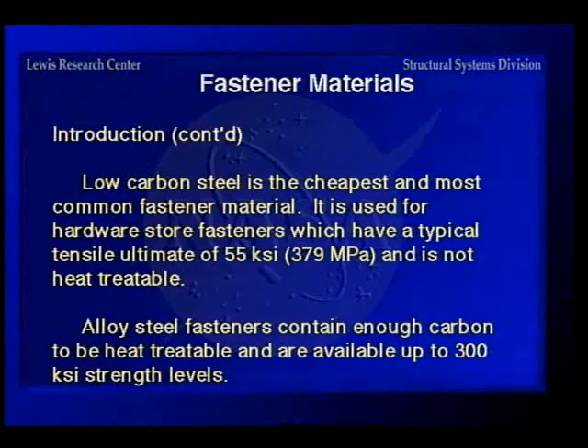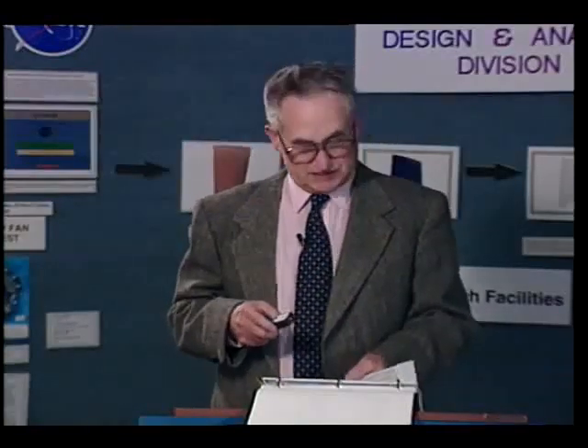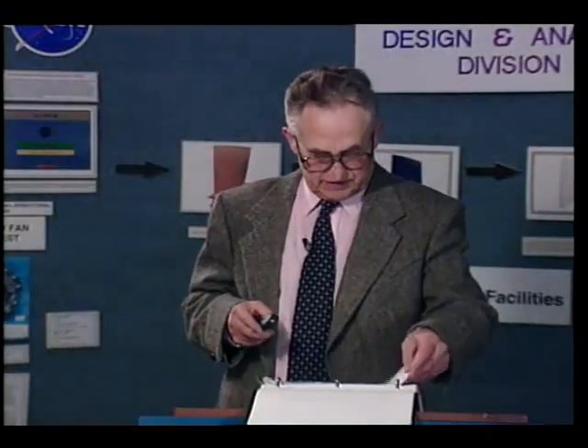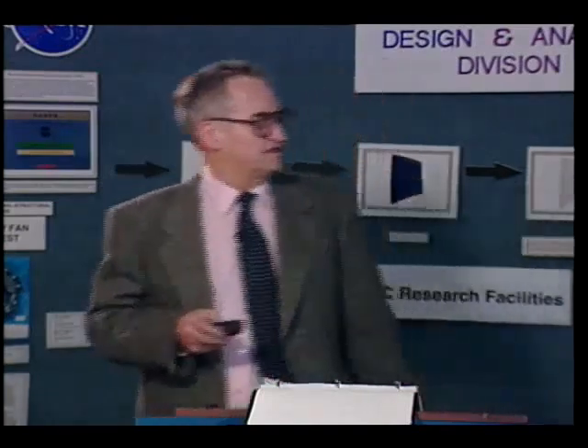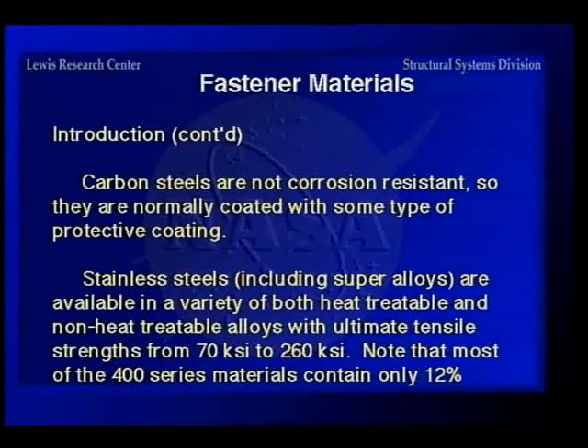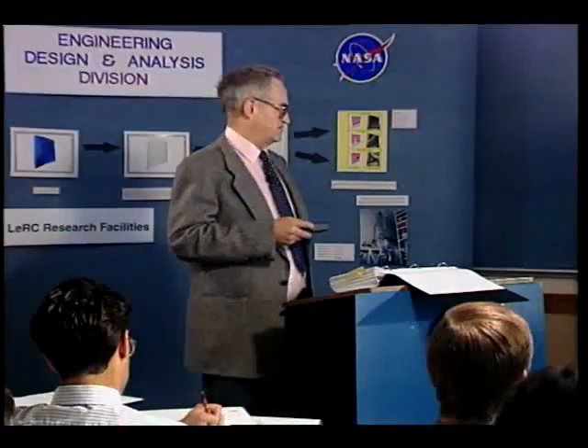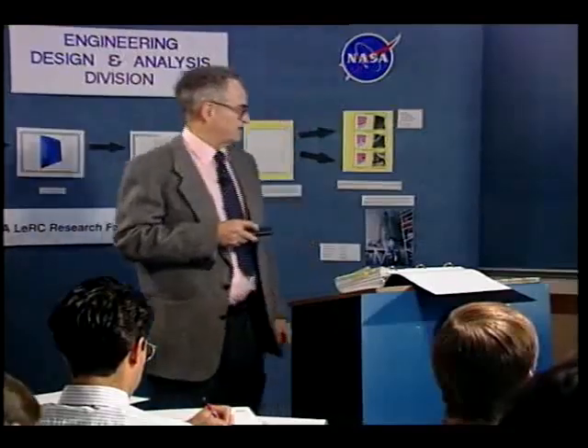So now the alloy steel fasteners, you can get them up to 300 KSI, KSI being 1,000 PSI, so it's 300,000 PSI strength levels. But I'll try to point out to you here that in most cases you really don't want to do that. Now, carbon steels are not corrosion resistant, so they usually have to have some kind of a coating to protect them from rusting. And the stainless steels you can get in all varieties of both heat-treatable and non-heat treatable alloys with tensile strengths of 70 KSI to 260, the 70 being the ordinary 300 series stainless that we use here all the time. And the 260, you're talking work-hardened Inconel 718 or A286.